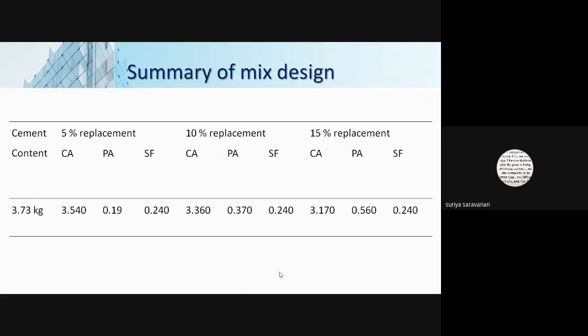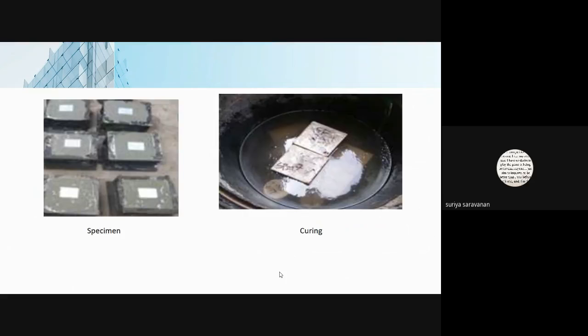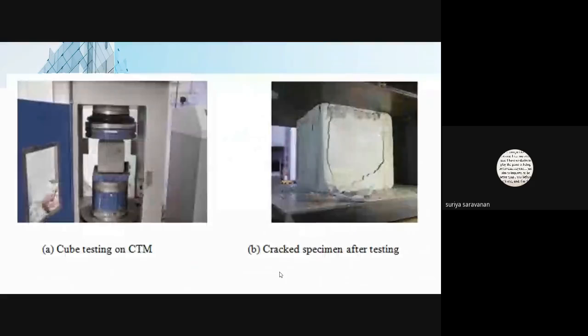And for each of them, we have added 3% steel fiber of the total weight of concrete, which comes to 240 grams of steel fiber. So we have added that also. And we have cast our cubes. You can see the cubes. They have been cured, and the testing has been done for 7 days, 14 days, and 28 days. Then you can see the cracked specimen after the testing also.